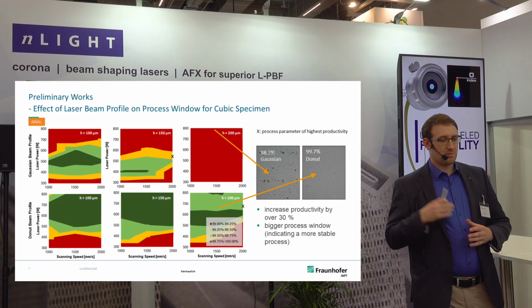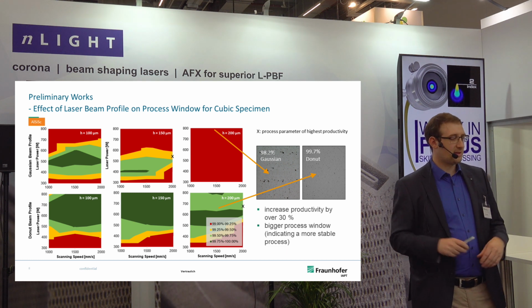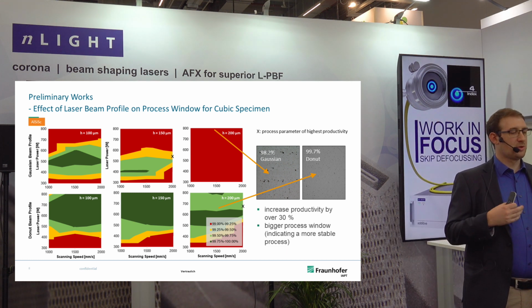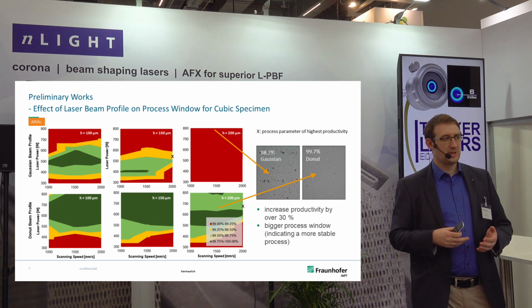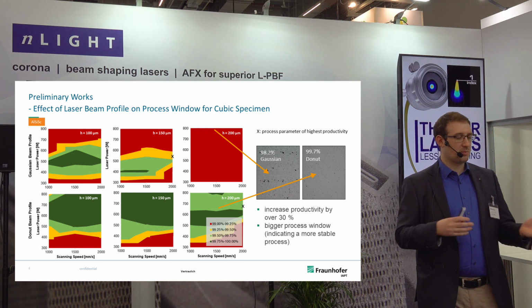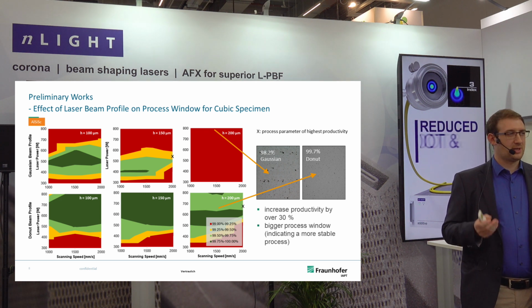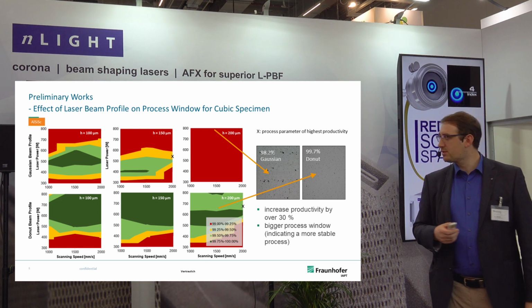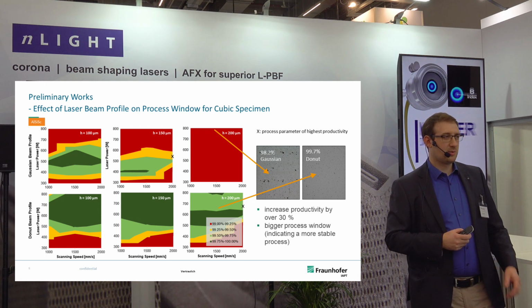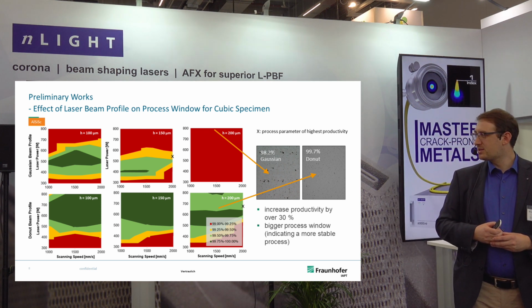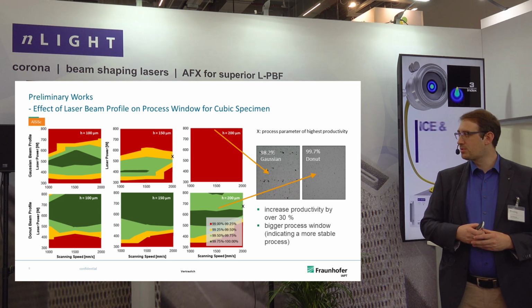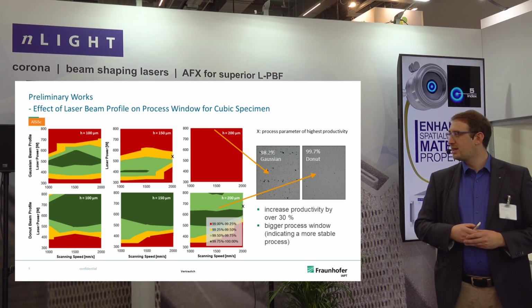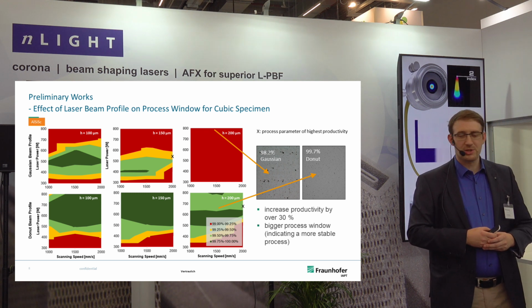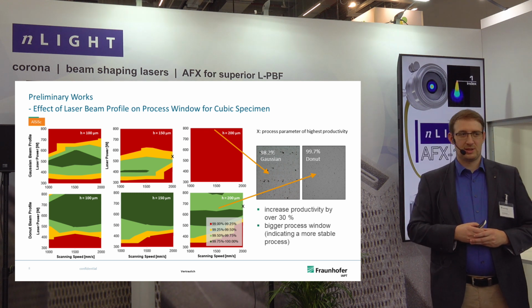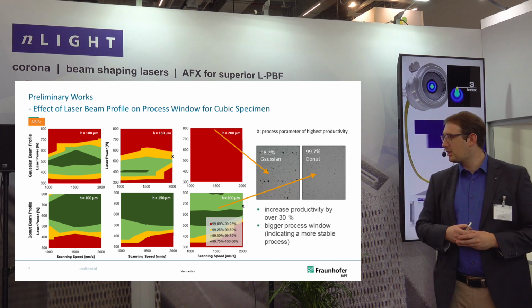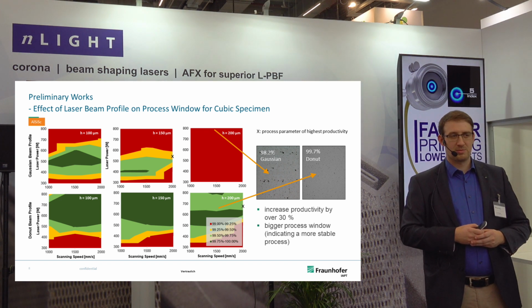Then we tried, okay, from single tracks it's a nice finding, but what if we produce three-dimensional cubic specimens to see if the process works, so that we can get an idea about the productivity. In this case, it was an aluminum silicon scandium alloy. You can see on the top row, for different parameters, the relative density we measured, colored here in green almost 100% density, and red 99% density.